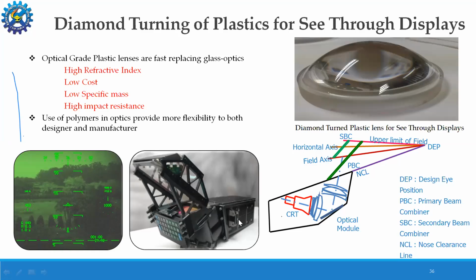So we have tried to replace the glass optics with plastic aspheric optics, designed and developed by my group by ultra precision diamond turning. The greatest advantage of replacing the glass optics with plastic is that, as we are moving from spherical to aspheric, there is definitely a reduction in distortion and aberration, and there is a reduction in weight by 30%. So this was the major achievement in this work.